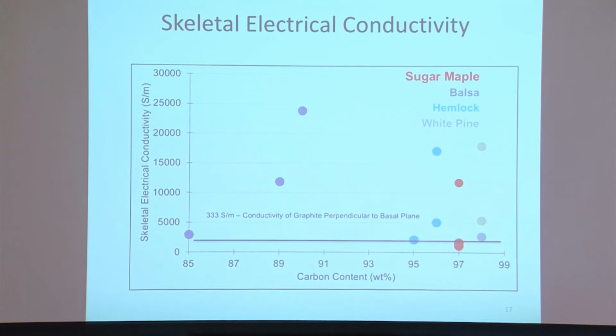As I mentioned several times, conductivity is one of the properties we pay attention to because it's one of the key properties for electrode materials. So we look at the conductivities of biocarbon derived from different woods. What you can see here is that there's a strong correlation with the carbon content of the biocarbon, which is not so surprising. One important thing is that the highest conductivity is over 25,000 Siemens per meter, compared to about 300 Siemens per meter for graphite perpendicular to the basal plane.